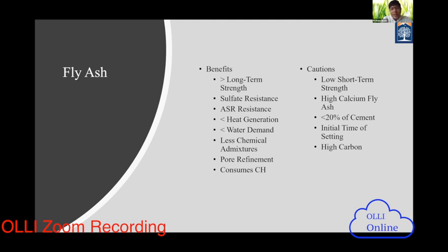And then what are the challenging parts to deal with fly ash? As I mentioned, initially short-term strength could be low. So we do not need to get scared that the short-term strength is a little bit lower than concrete. But in the long term, we are talking about long-term durability and strength. So that is really good.